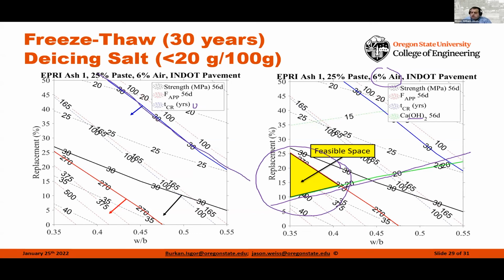I also noticed there's a question on air entrainment. What I would say here is, there could be a third axis that we draw, which is the amount of air inside of the system. As this air content gets smaller and smaller, this yellow triangle gets smaller and smaller. As the air content gets larger, this forms almost a pyramid shape inside of those mixtures to account for the role that air plays. This allows us to compensate for the fact that when we add air, compressive strength may decrease, but our freeze-thaw resistance is going to be beneficial, and we can play those trade-offs in a meaningful and numeric way, as opposed to just using rules of thumb.